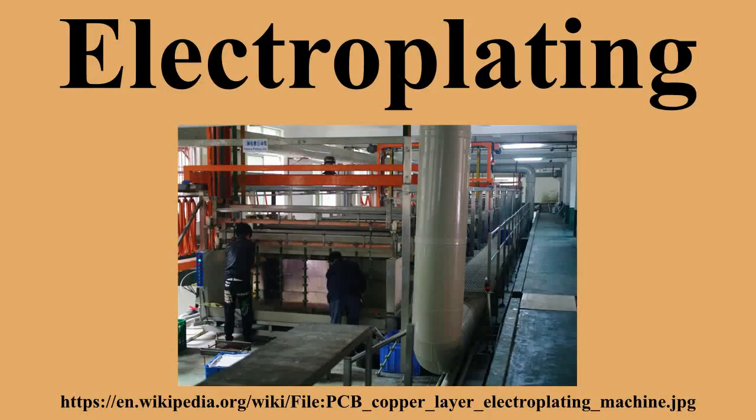It is filled with a sample of the plating solution, and an appropriate anode which is connected to a rectifier. The work is replaced with a Hull cell test panel that will be plated to show the health of the bath. The Hull cell is a trapezoidal container that holds 267 milliliters of solution.